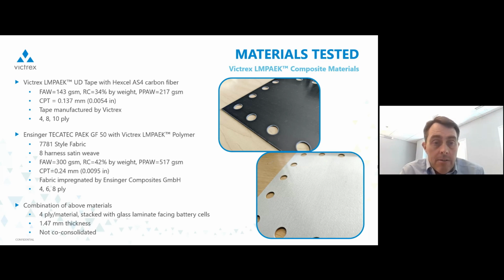The next one was a 7781 glass weave from Ensinger. It's their TECATEC PAEK GF50 product, and again, that's got Victrex's LMPAEK polymer. It's an 8 harness satin weave. It's about 1/4 of a millimeter thick. So then we went with 4, 6, and 8 plies thick on that. Lastly, as a bit of a curiosity, we had a little bit of time left over, and simply stacked some UD plies with some glass plies, not consolidated, but just stacked them together in a combination to see what would happen. And in this case, we had the glass facing the battery cells and the carbon on top. Next one.